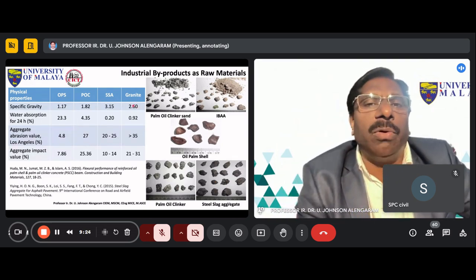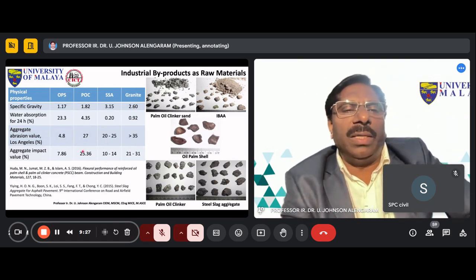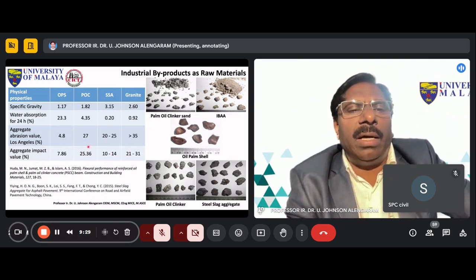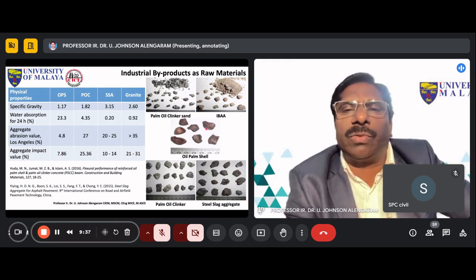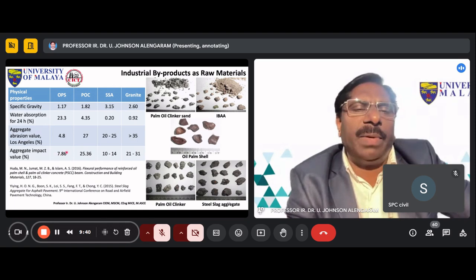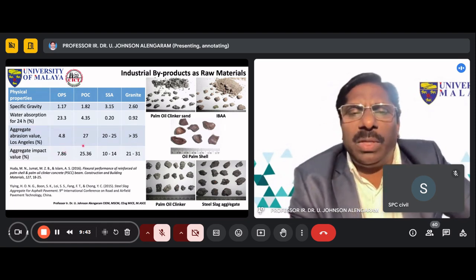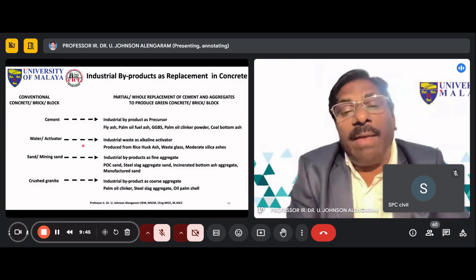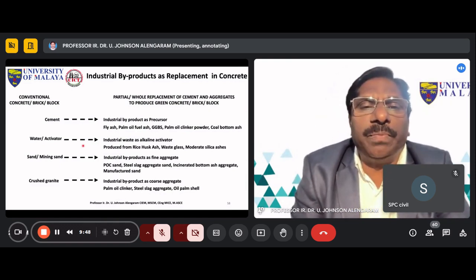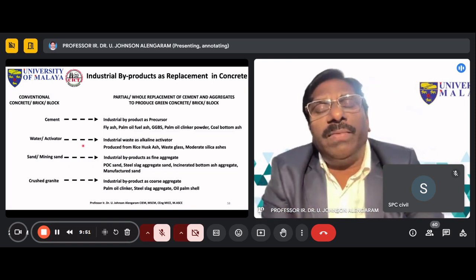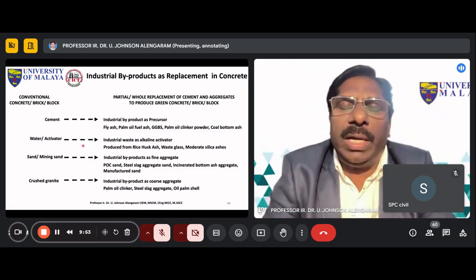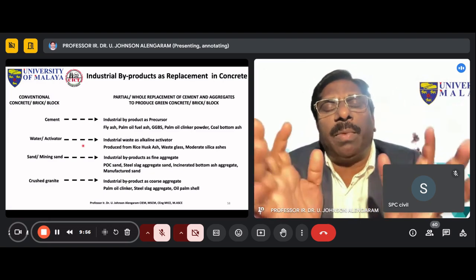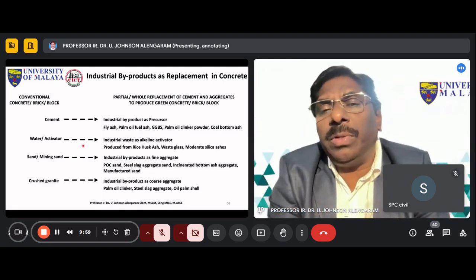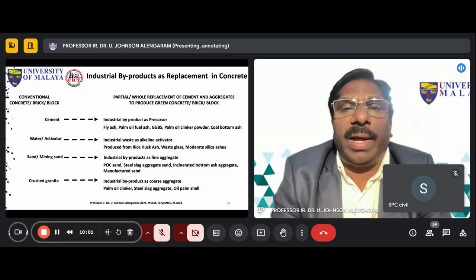We use the crushed granite as a coarse aggregate. However, if you look into the aggregate impact value, the conventional crushed granite is almost 20 to 30%, whereas for the oil palm shell it is only 7%, sometimes 4%. So that shows something unique. Therefore, we have developed a concrete, which I can show later, that can be used even in earthquake-prone regions like Indonesia and some of the disaster zones. Some lightweight concretes can be developed using these materials. So this one I have already explained.